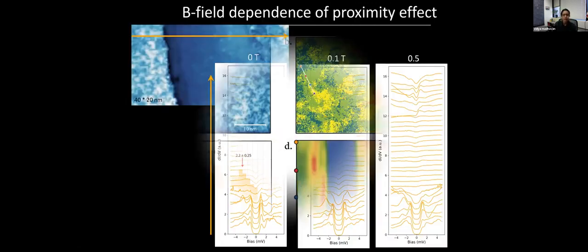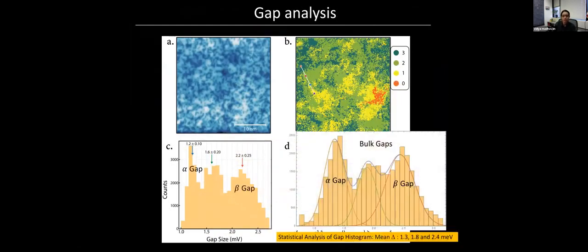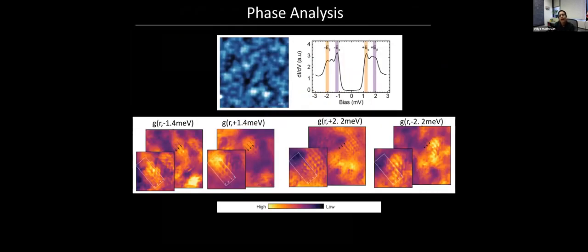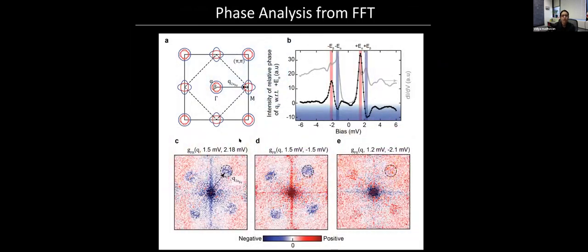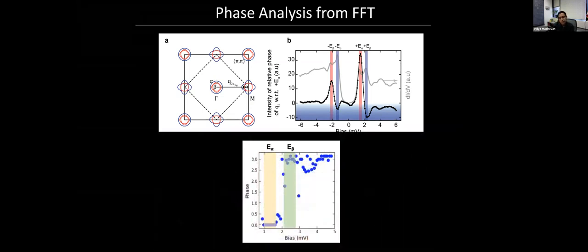But in the interest of time, I'm going to skip over all this and just show you one interesting thing, which is that with STM, you can do a phase analysis and ask the question, what is the relative phase of the order parameter in these various pockets? By doing this phase analysis, what we found is that not only is there a phase shift between the hole pockets and the electron pockets, but there's also a relative phase shift between the two hole pockets at the gamma point, which is very much in line with Jiangping Hu's prediction.